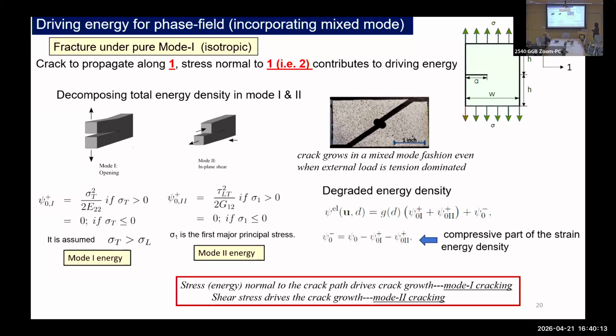Okay, and correspondingly, we have the degradation in the elastic energy. So this compressive part is taken out from the total energy density. This is what is important to note. It's not, as I said, purely isotropic material-like behavior, right? So just looking at the crack path, you cannot determine whether it's a mode 1 or mode 2 crack growth, right? You have to look into the local stress, or the corresponding energy which is driving the crack growth, to make sure whether it's a mode 1, mode 2, or a mixed mode situation.